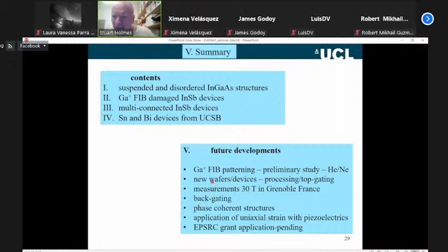I'm trying to sort out backgating. If you have control over the backgating, you have much more control over the electrostatics of the wave function confinement in the system. I want to develop further these phase coherent structures. I also want to develop strain. If you bond your device to a piezoelectric crystal, by applying a voltage, you can change the strain in the layer. We know in the tin, particularly, the strain is very, very important. And I applied for funding on this to our national funding body, the EPSRC. So hopefully that funding will come through.